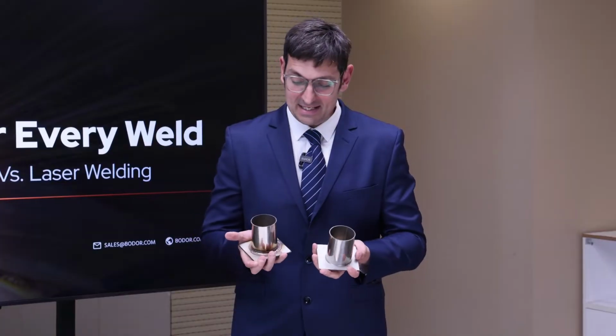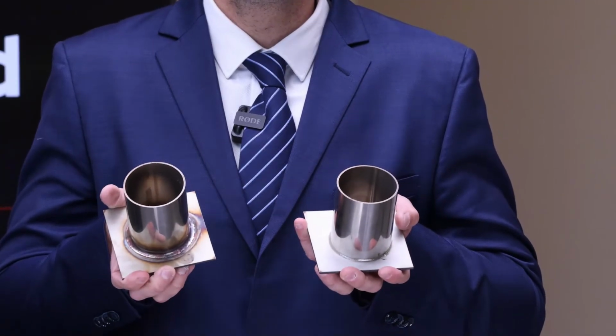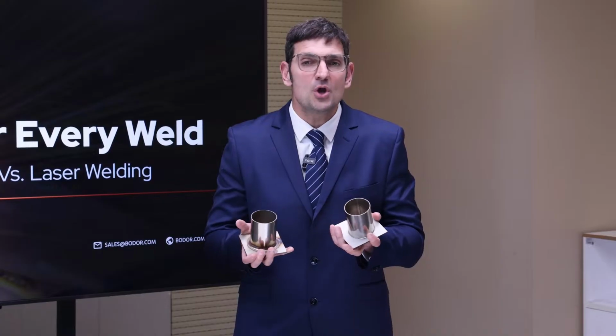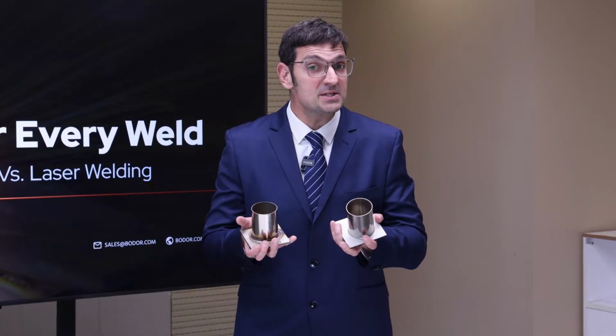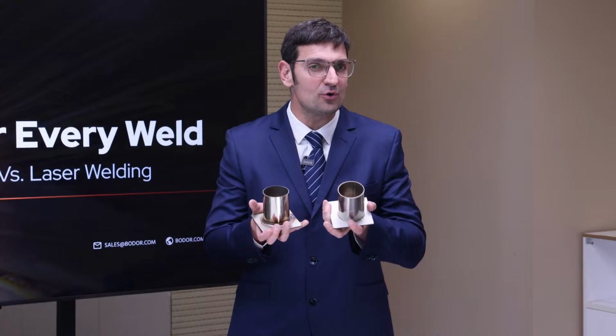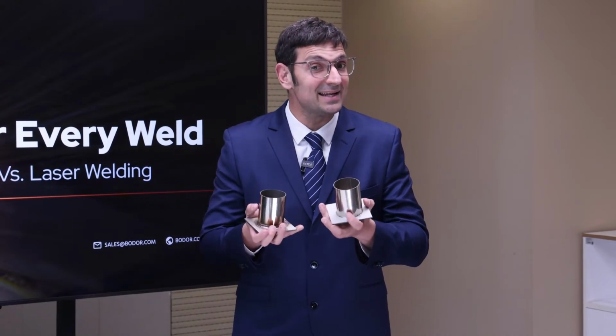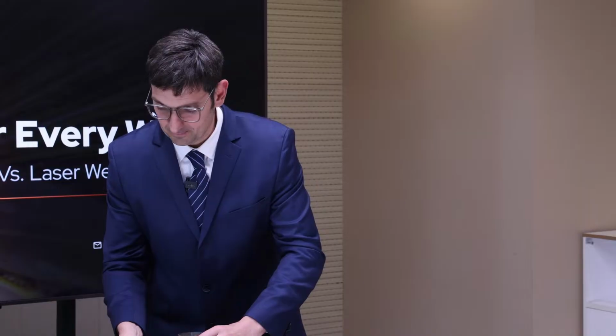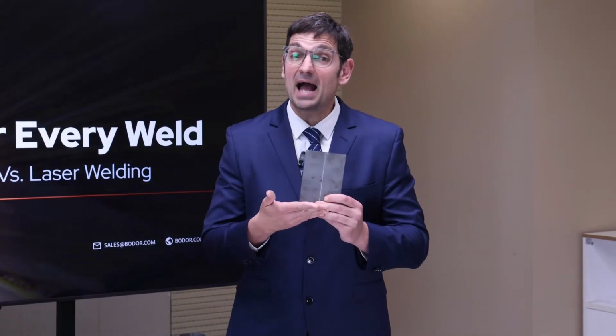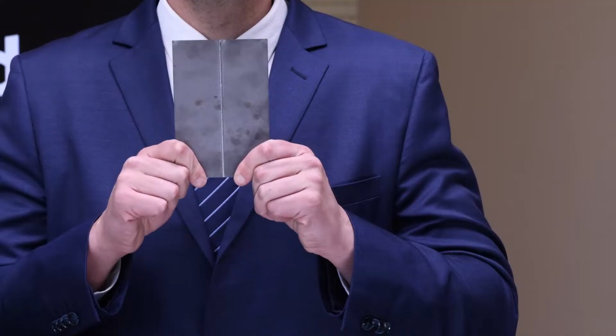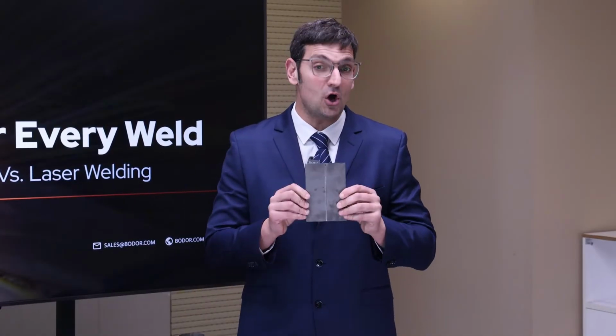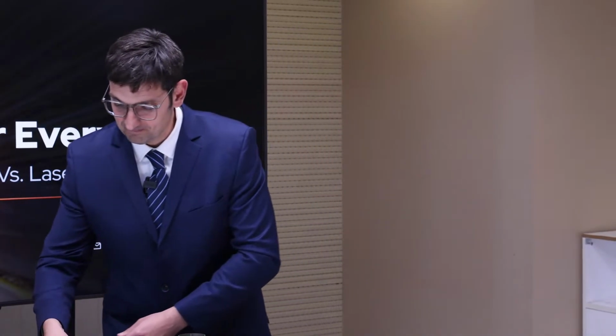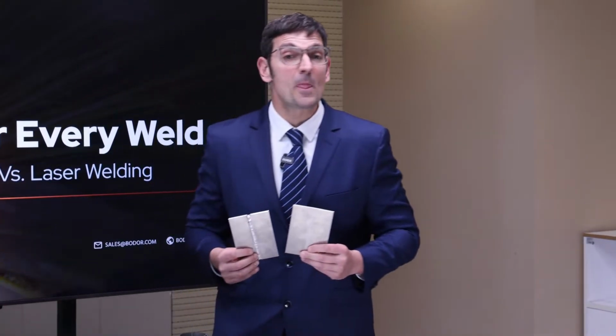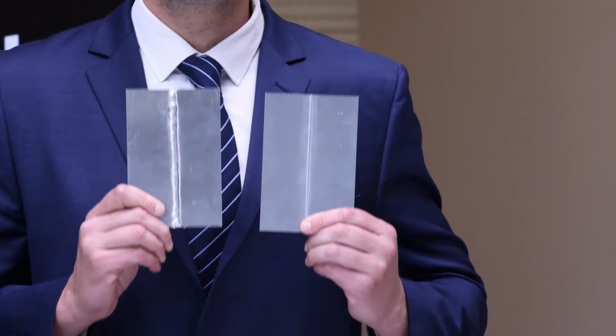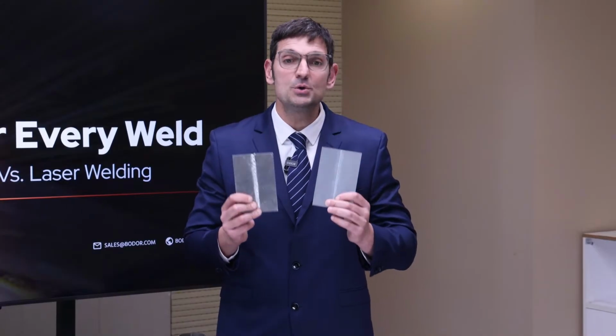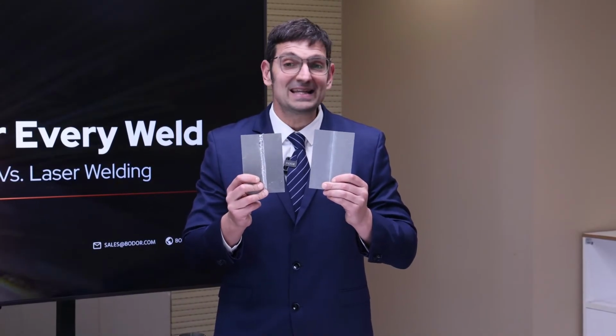You can see how clean and consistent the laser weld is. The seam is tight, smooth, and shows almost no spatter or discoloration. And the best part? This level of quality holds across different materials, not just stainless. Take carbon steel for example. The weld is sharp, clean, and shows minimal surface oxidation. With aluminium, which can be notoriously difficult, the laser still gives you a bright, clean seam with hardly any soot